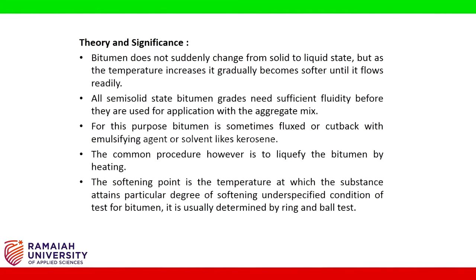As the temperature increases, bitumen gradually becomes softer until it flows readily. All semi-solid state bitumen grades need sufficient fluidity before they are used for application with the aggregate mix. For this purpose, bitumen is sometimes fluxed or cut back with an emulsifying agent or solvent like kerosene. The common procedure however is to liquefy the bitumen by heating.